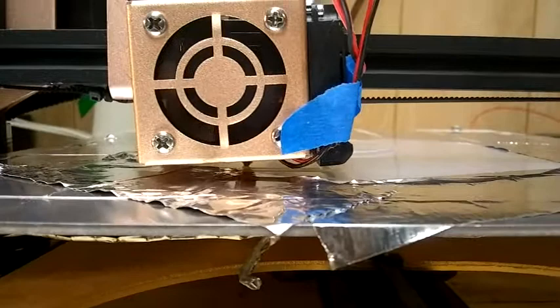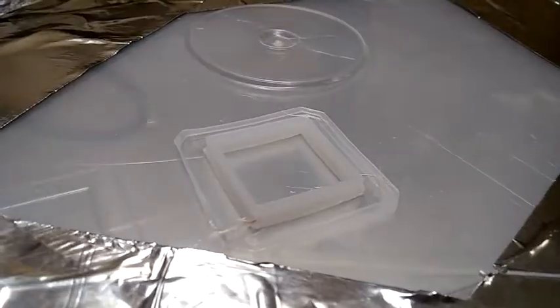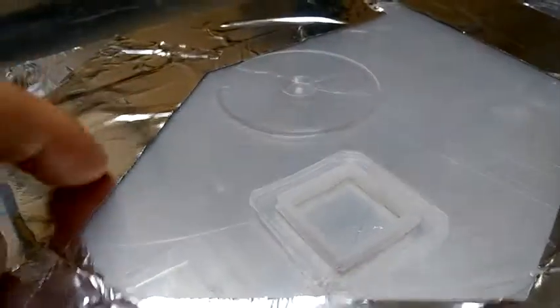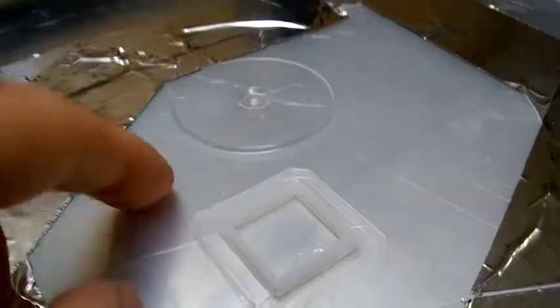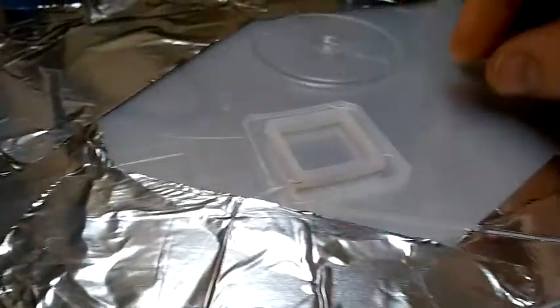So far so good — I'm surprised this is working. This one came out okay. The material really does tend to warp at the corners, so the thicker the substrate the better, and the more taped down it is the better, just so the corners don't warp up and bring the substrate material with them. I tried printing on polypropylene packing tape but it was just too thin — it would just pick up with the corners.